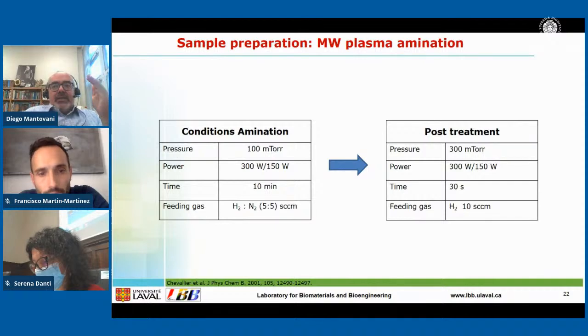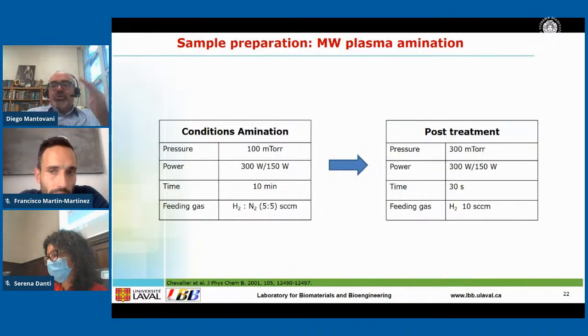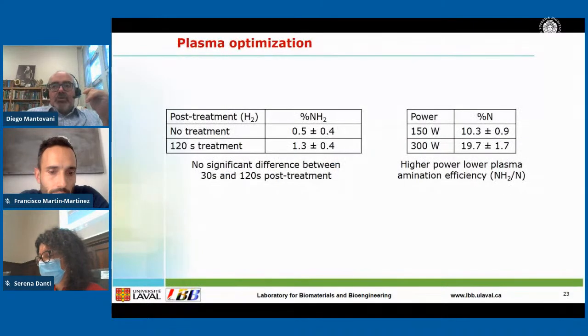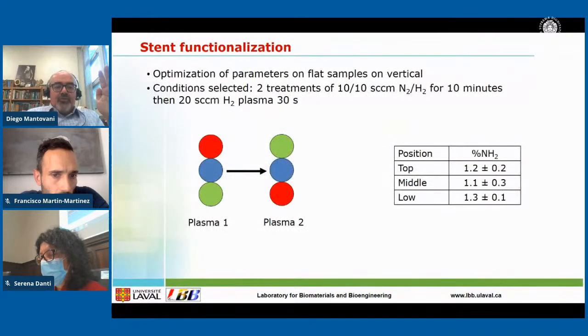Amination was done with a different condition, basically in a post-treatment, and the plasma optimization arrived at a value of 10 to 20% of nitrogen, which results in around 1.5% of amine group. This is more than enough. Don't think that we need 100% of amine group on the surface.